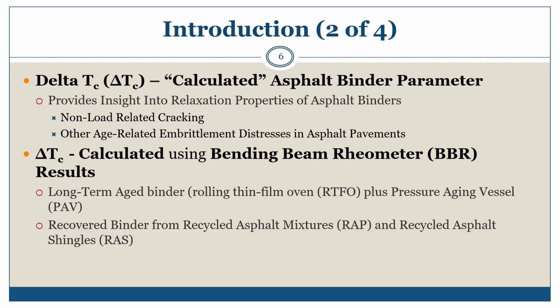The difference in low temperature performance grade PG limiting temperatures, delta T critical, commonly referred to as delta TC, is an asphalt binder parameter that provides insight into relaxation properties of the asphalt binder that can contribute to non-load related cracking or other age-related embrittlement distresses. Delta TC is a calculated value using results, creep stiffness and creep rate, from the bending beam rheometer BBR test.